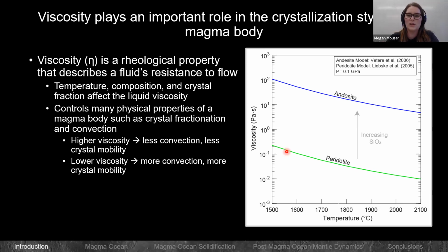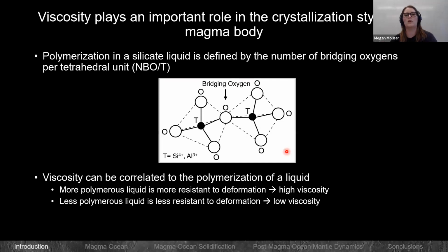To dive a little deeper into the silica composition part of this, viscosity can be related to the polymerization, which in our silicate systems is defined by the number of bridging oxygens per tetrahedral unit. We have our silicate structure, the thing that makes all of our silicate minerals, that has a tetrahedrally coordinated cation, which more often than not is silicon 4+, but sometimes can be other things like aluminum 3+. The polymerization is defined by how many of these you can link together. If you have an isolated unit, you're going to have something very low in viscosity and low in polymerization. If you have something that's very connected, it'll be very polymerized and high in viscosity. That's how that relation comes about, and we're going to see that a little bit with some of these Mercurian liquids.